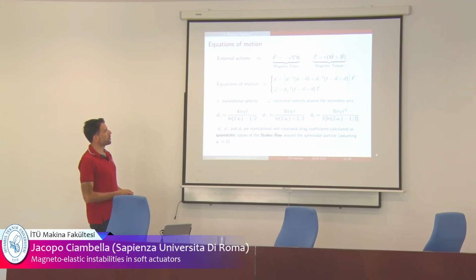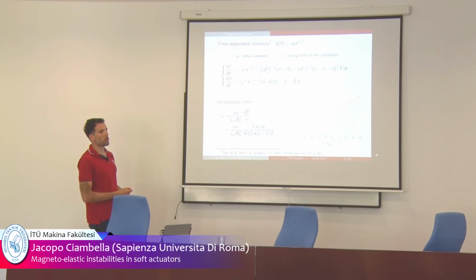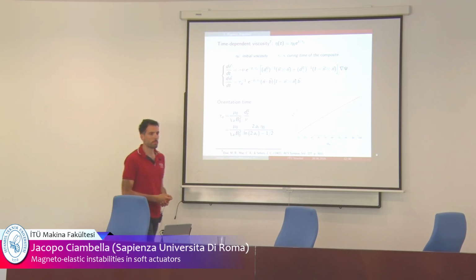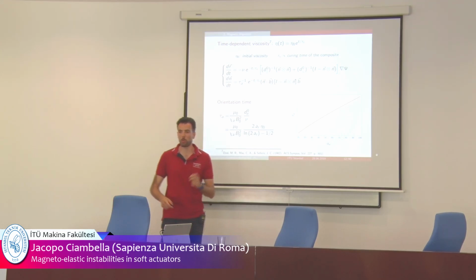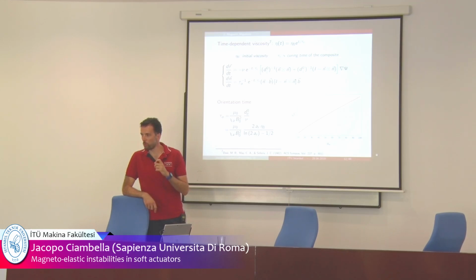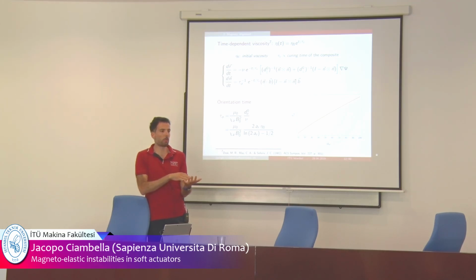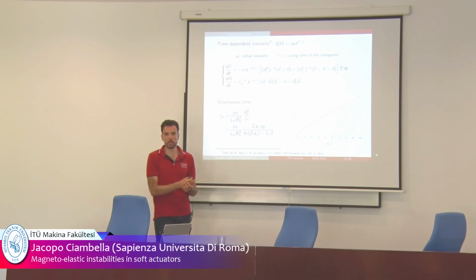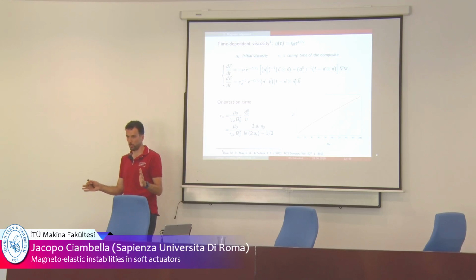So we can do something more. For instance, take a viscosity which is changing with time, because this is exactly what is happening when you manufacture the specimen. You disperse the fiber into the specimen when it's still viscous, but then it starts to solidify, becomes solid, because the composite is curing. So you can assume that the viscosity is increasing with time exponentially. When the viscosity is infinite, it means that the material is fully cured, so it's solid.